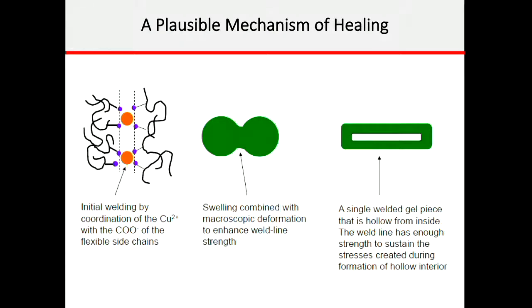So the explanation was that the initial welding takes place by the coordination of the cupric with the carboxyl of the flexible chains. This swelling is then combined with macroscopic deformation, which enhances the weld line strength, and then you get a single welded gel piece that is hollow from inside.